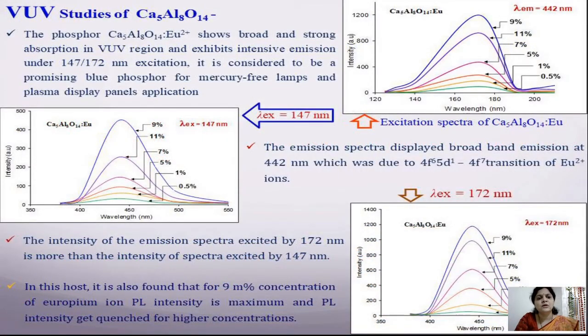VUV study of Ca5Al8O14. The first graph shows the excitation spectra of the material, and the other two are the emission spectra, one at 147 nanometer and the other at 172 nanometer excitation. The first graph shows broad and strong absorption in the VUV region and exhibits intensive emission under 147 and 172 nanometer excitation. It is considered to be a promising blue phosphor for mercury-free lamps and plasma display panels application.